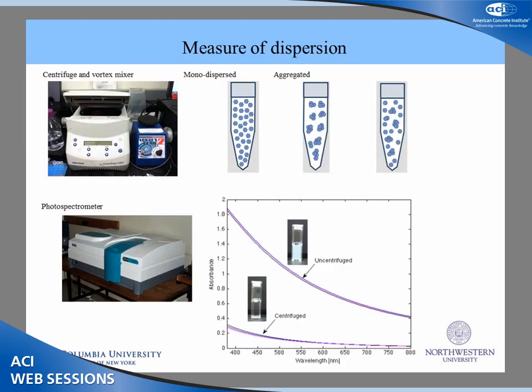So one important component of the study is measuring dispersion, and we did this through spectrophotometry. Basically, you have your suspension, and then you measure the absorbance of the supernatant before centrifugation, and then you get an absorbance spectra like this. And then after centrifugation, you compare the supernatant, and then compare the absorbance at a certain wavelength, and that gives you a quantitative measure of sedimentation.